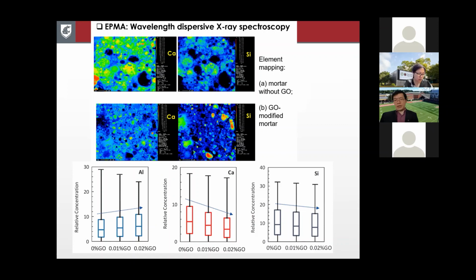No, the opposite. Basically, where there is graphene, they repel the negatively charged aluminum tetrahedrons away from them. So those aluminum ions would enter the pore solution and participate in the hydration process and be found in the hydrates. On the other hand, the calcium was captured by the graphene oxide nanoplates and therefore did not participate in the hydration process. Therefore in the hydrates, you have less calcium. Does that help? Yeah, it does.